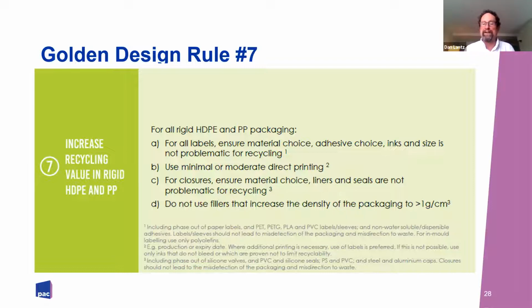Use minimal or moderate direct printing. Again, that's because we don't want to have the inks causing problems for the recycling process. Ensure that the closures are not problematic for recycling. Now, they don't speak really specifically to the liners in the seals, but for a PET bottle, for example, don't put a PVC liner in it, because as soon as you shred the PET bottle and the liner gets pulled off, the liner is going to sink with the PET. And then all of a sudden you've got PVC mixed in with the PET. And as I mentioned earlier, now that's causing problems for the PET recycling. The same thing applies with PETG and PLA, all of those things, that they all sink with PET.